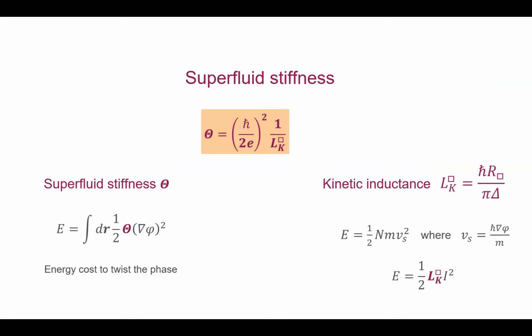One way to measure it is via the kinetic inductance of the superconductor. There are other ways, like measuring the penetration depth with two-coil inductive measurements. Here, what we do in our measurements is a direct measurement of the kinetic inductance, which, as you see, is proportional to the resistance of the film, so disorder, and inversely proportional to the gap of the superconductor. And the superfluid stiffness is simply given by the flux quantum squared proportional to 1 over L_K. For circuit people, this is a very well-known formula. This is nothing but the Josephson energy, for an SIS Josephson junction. You see that when the critical current is small, E_J is small, and the stiffness is small, so you very quickly twist the phase across your junction or across your superconductor.